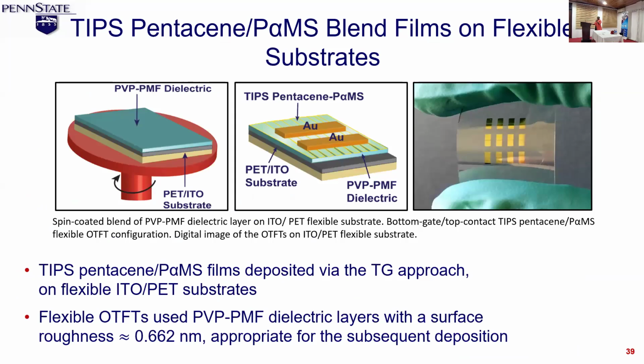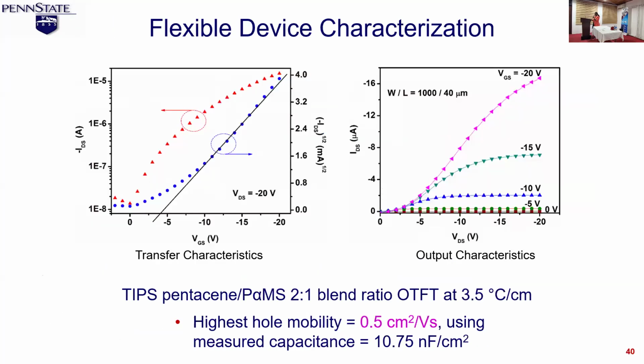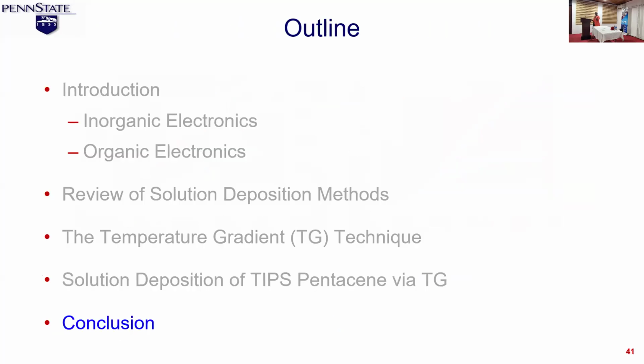And then the last thing I did was to test it on a flexible substrate. So throughout, I had used a rigid silicon. And what I did was to now actually create it on a plastic substrate. And that actually gave me the best performance. So that brought our mobility to 0.5, so at least more than 10 times higher than just doing the pure systems. Okay. And that is pretty much the work. Okay.